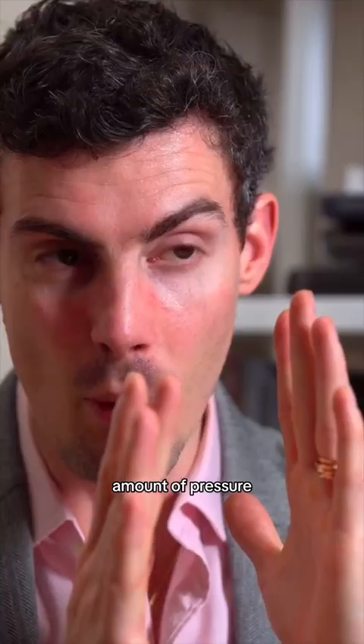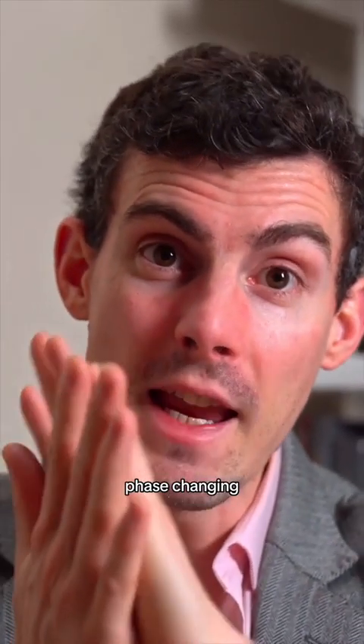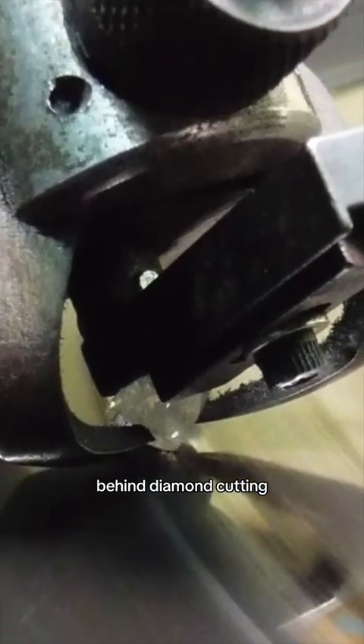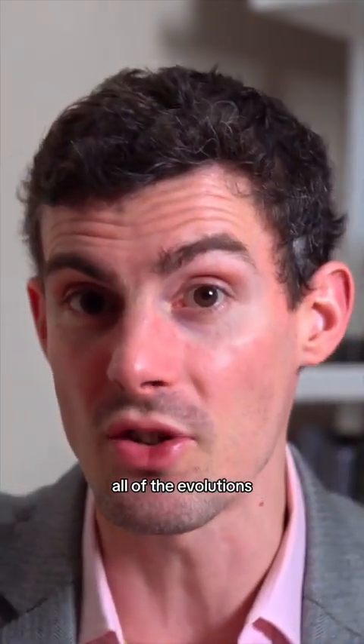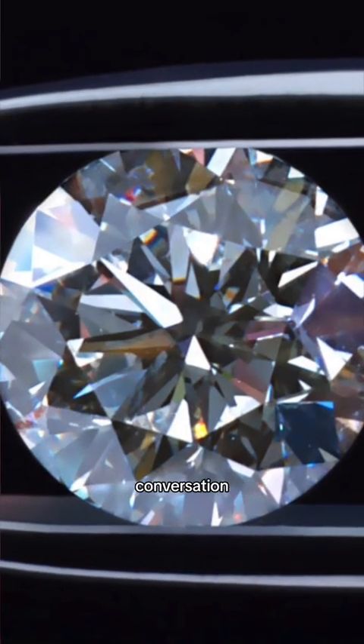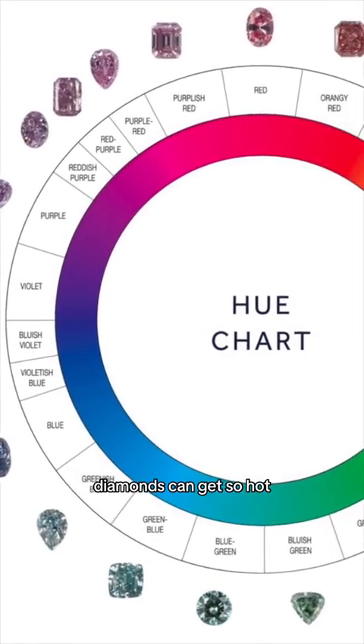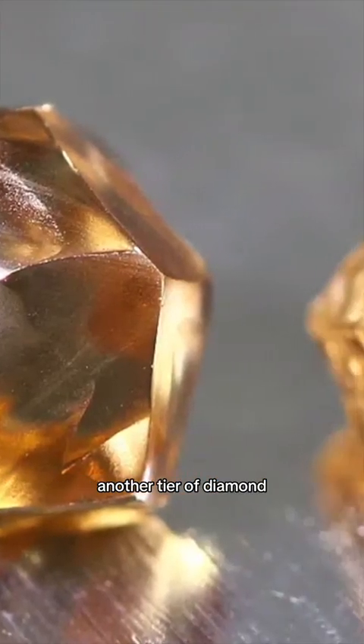Diamond cutting involves an enormous amount of pressure. We're not even certain that the abrasion is actually polishing the diamond — the surface under the pressure and heat may actually be phase-changing the diamond crystal to make it polished and smooth. We're essentially pulverizing the diamond and turning it into carbon, which is how you get a polished surface rather than tiny score lines. There's a little mystery behind diamond cutting. Additionally, a lot of colored diamonds have a skin of color, and diamonds can get so hot during cutting that they can turn red and then brown — so you have to be very careful. Colored diamonds are like another tier of diamond cutting altogether.